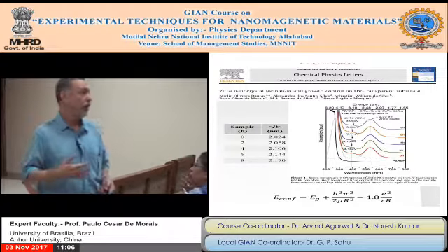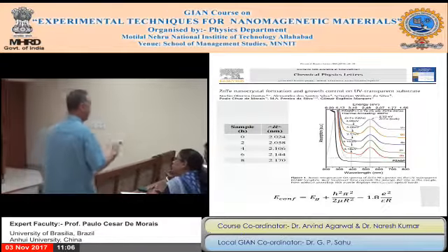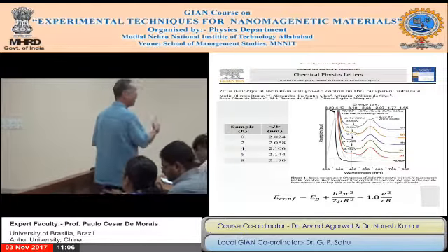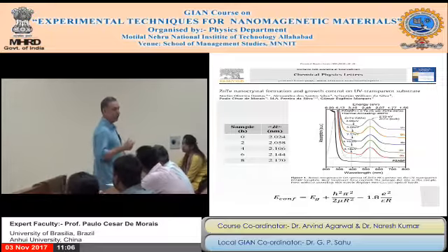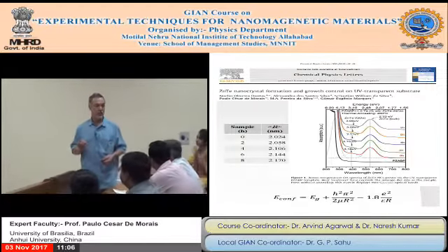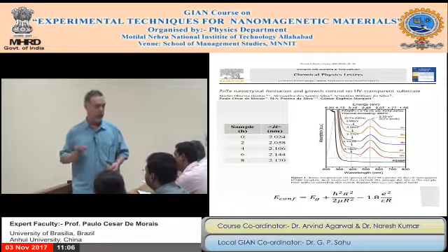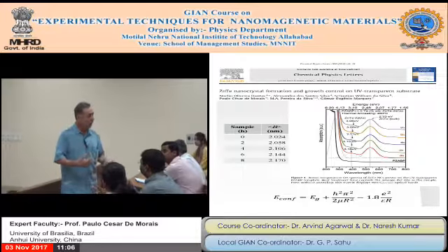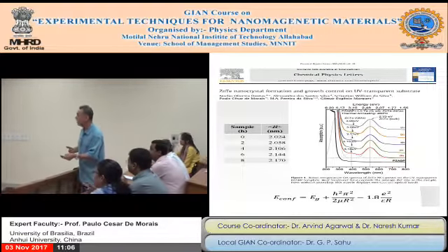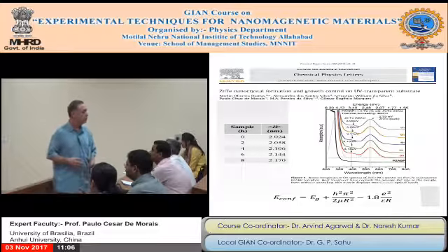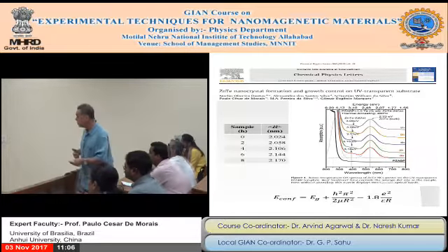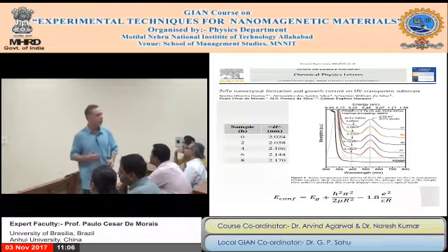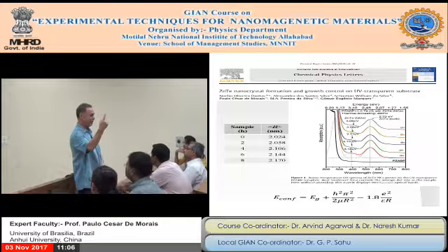If, in your optical experiment, you pump the laser hard, what you do is generate a lot of carriers, electrons and holes. And once you generate a lot of carriers, this effect becomes very important. And so this equation is not valid anymore, because this equation is supposed to be for a single particle.